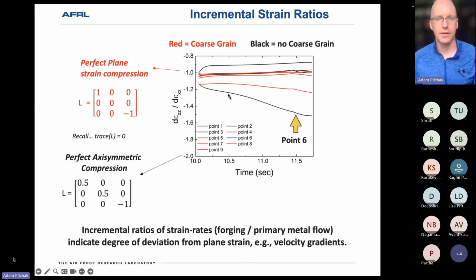And so for my various points here, I've plotted the ratio of that strain in the forging direction to the strain in the primary metal flow direction, and color coded them according to whether or not those specific locations had the coarse grain phenomena or not. We can see that all of these positions that were quite close to perfect plane strain compression absolutely had abnormal grain growth. There's this one outlier that's maybe 20% away from perfect plane strain compression, it still developed abnormal grain growth.